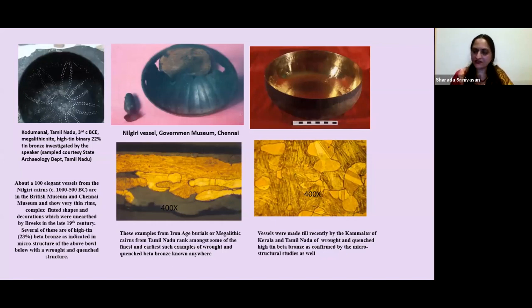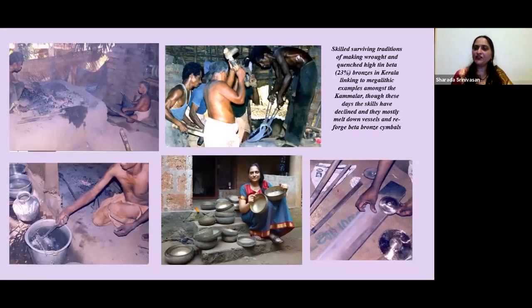And you see the same kind of structure right into recent times, which points out how useful and important it is to make ethno-archaeological observations. So just to take you through some of the steps that I was talking about, you're seeing on the corner there this ingot of high-tin bronze being heated on this anvil, which was then, in those days, worked by bag bellows by the Kammalar. And then there are these consecutive cycles of heating, forging, annealing, and heating again until this beautiful shape is obtained. And then it is very rapidly quenched in water to retain that martensitic beta phase. And so many of these vessels are just being recycled these days because although the vessels have gone a bit out of vogue, that martensitic beta property of musicality is still much sought after. So they still make musical vessels of this material.